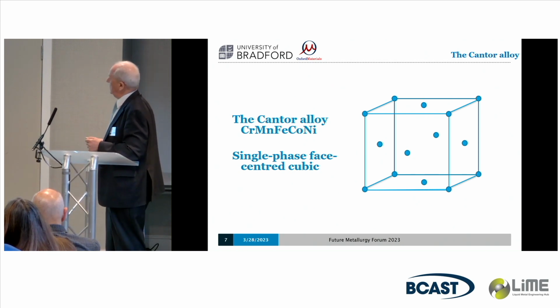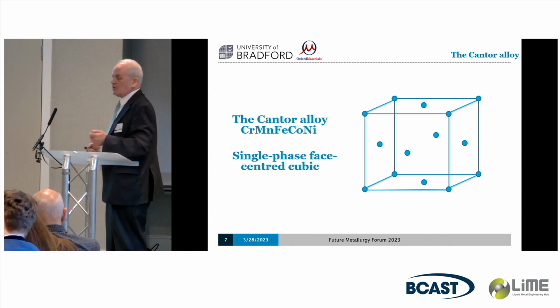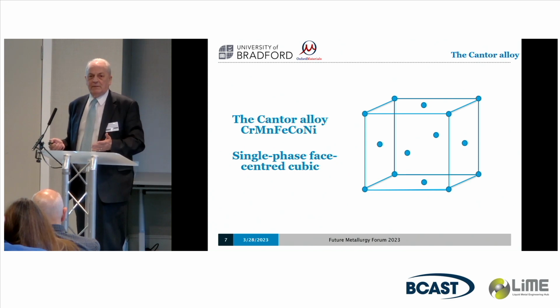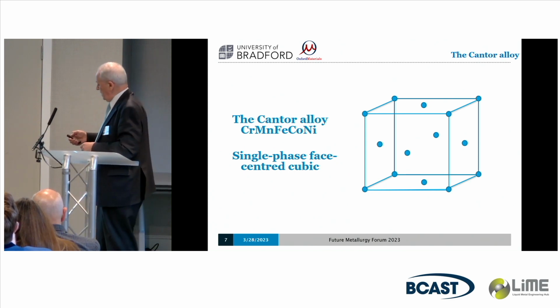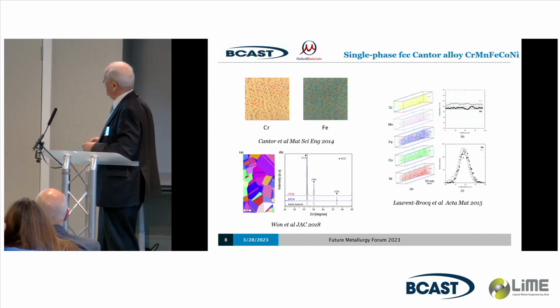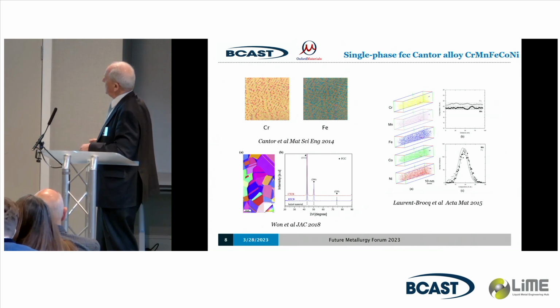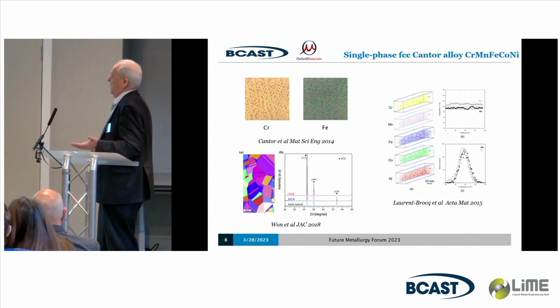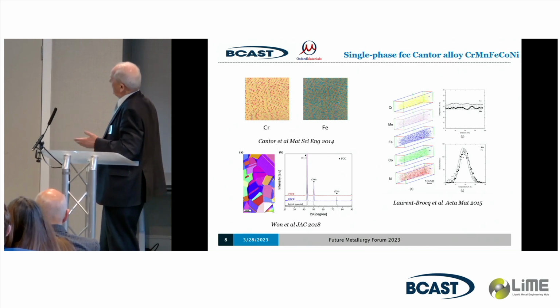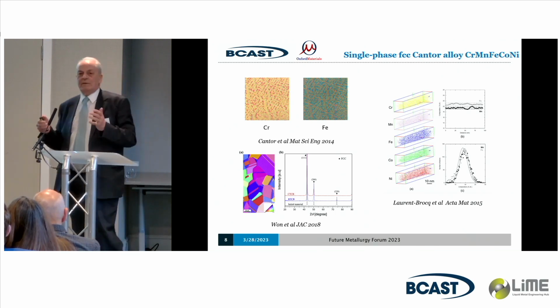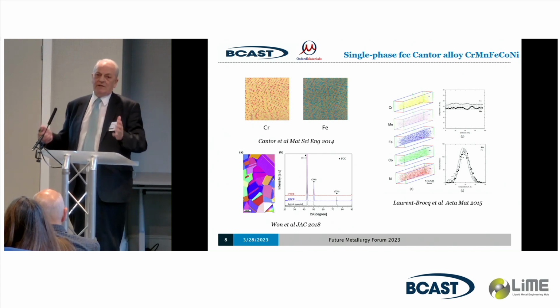Only one of these 5 components is FCC in its natural form, which is nickel in its room temperature form, and they don't mix with each other fully in solid solution in binary systems. So this was a remarkable surprise. And I'm just going to show you slightly more pictures of it. This is when it's solidified, it's dendritic, but you can roll it very easily. It's got tremendous ductility. You can roll it and recrystallize it, get beautiful recrystallized annealing twin structures here. When you do an atom probe or other things, you find that it's almost a perfect ideal material. Those atoms are distributed on a face-centered cubic structure almost perfectly ideally.